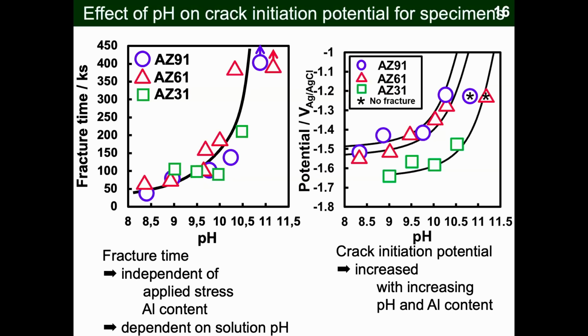Here is crack initiation potential depending on the pH. Crack initiation potential strongly depends on the pH here, and also on aluminum content. When you increase the aluminum content, crack initiation potential goes up. But this change does not correspond to this fracture time.